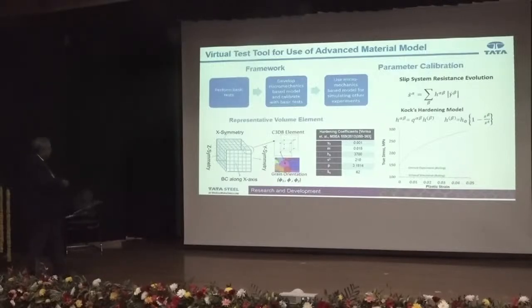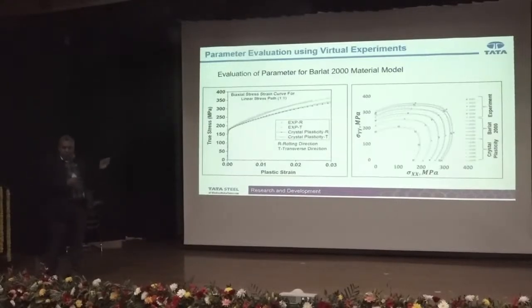So typically it works like this. Each of these cubes is representing one grain, and the orientation of these grains was calculated using EBSD. Then a micromechanics based model was implemented on top of that. These are the coefficients calibrated using the tensile test. So only the tensile test we did and calibrated the coefficients, and then we took these coefficients and started doing the biaxial, plane strain, all sorts of deformations.